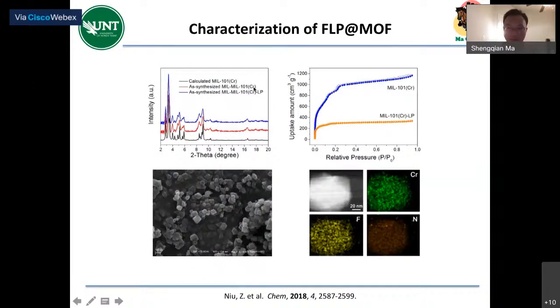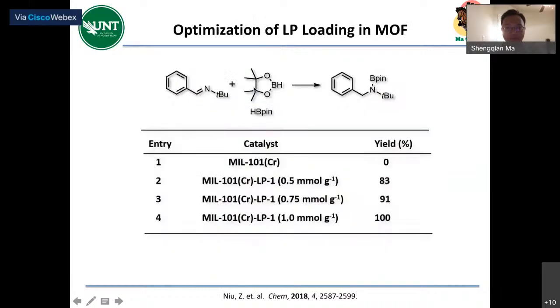Open metal site, chromium. So I will skip this. So first of all, when we load the catalyst, any catalyst in the MOF, there's always an optimal loading amount. It's not the less the better. It's not the more the better. Always the optimal. We figured out around 1 millimole per gram can achieve the highest activity.